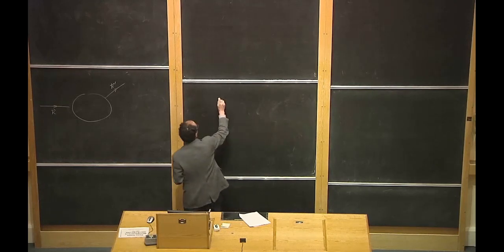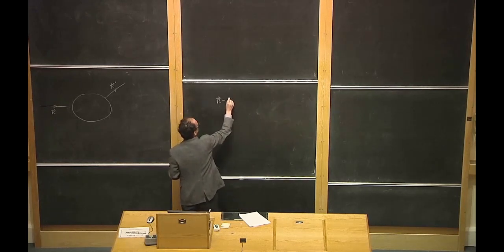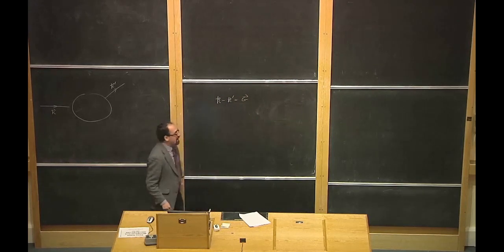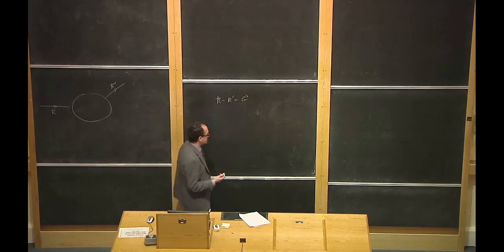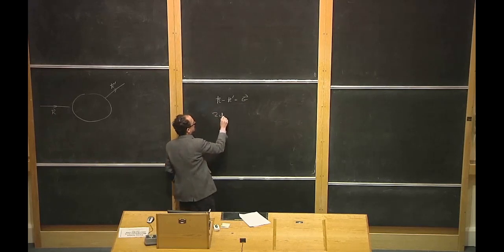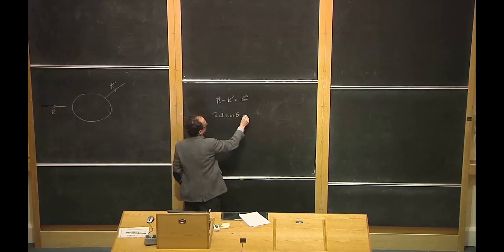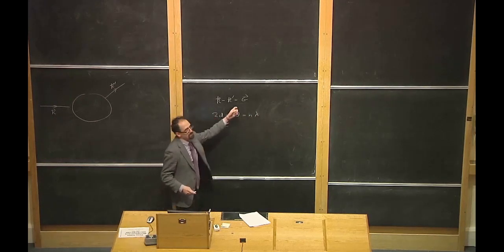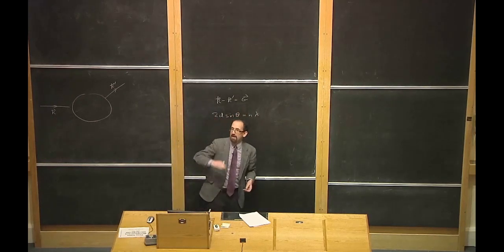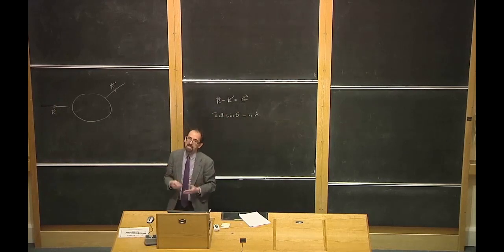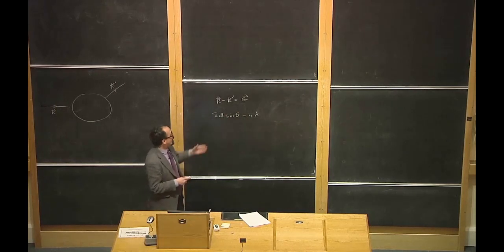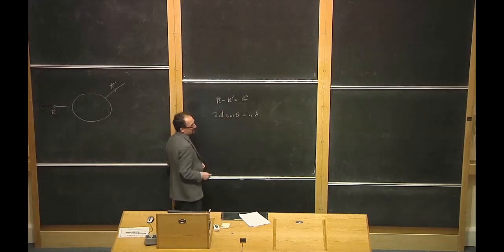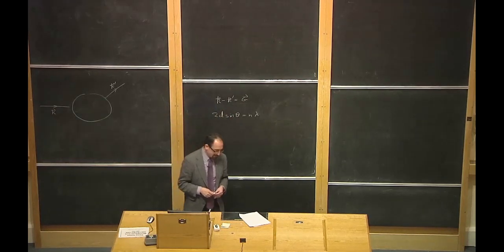First of all, in order to get scattering from k to k prime, you must have k minus k prime equal a reciprocal lattice vector G. And we derived in the last lecture that that's equivalent to the Bragg condition, 2d sin theta equals n lambda. In other words, since a reciprocal lattice vector is orthogonal to a family of lattice planes, what you're actually getting is diffraction off a diffraction grating with lattice plane spacing d orthogonal to that vector G.